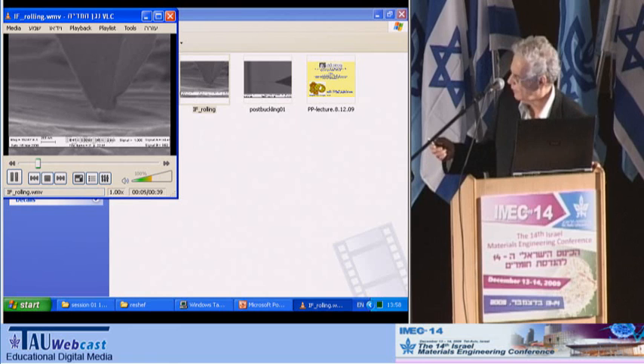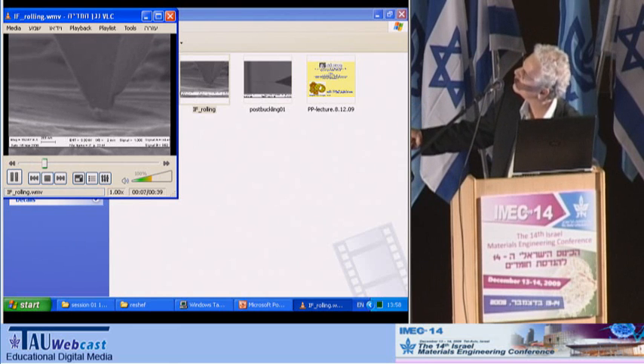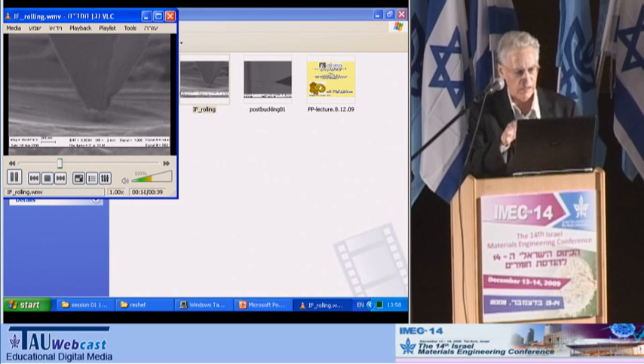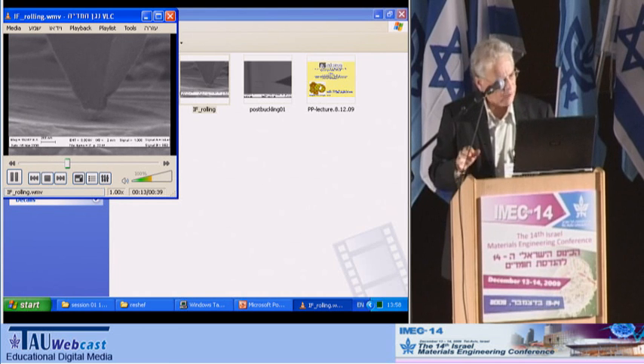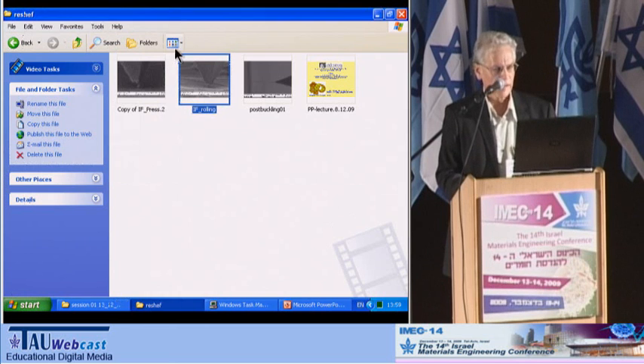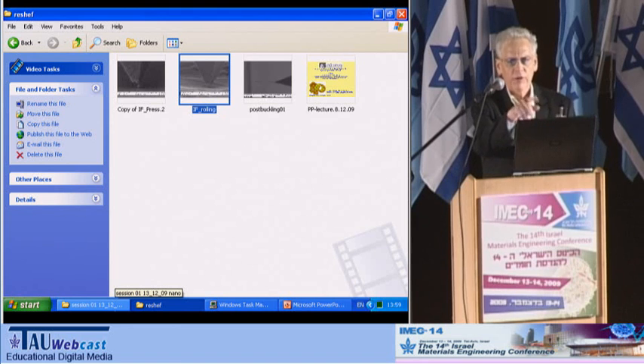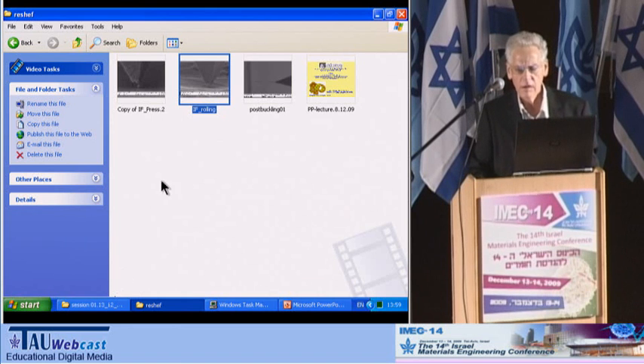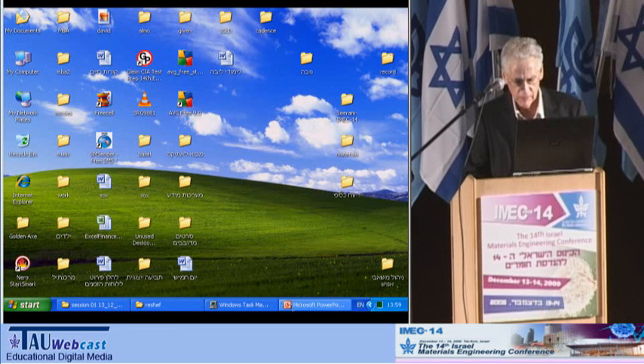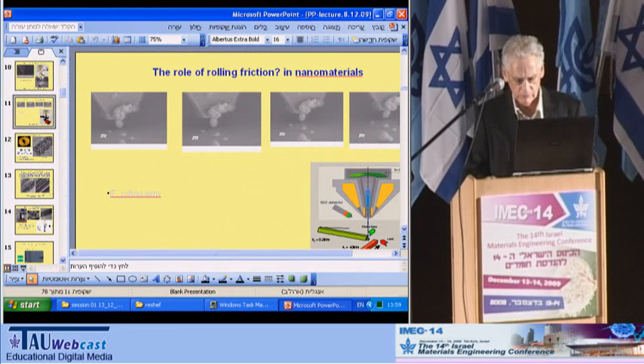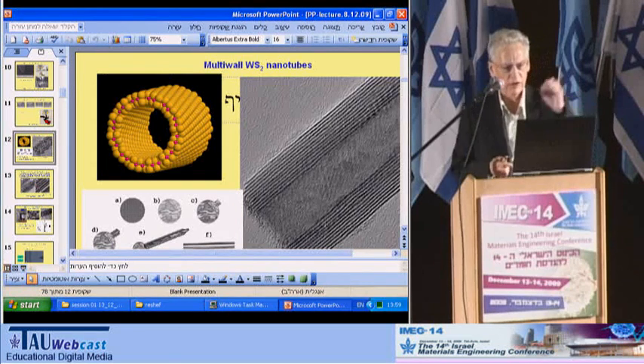You can see the nanoparticles. The nanoparticle is not only loaded, but it's sheared, and there is a very nice shearing process and rolling of the nanoparticles, and some sliding too that occur in this case. When the nanoparticles are entrapped in the contact area, it's more difficult for them to rotate, but nevertheless, they can do some of their rotation, and they can benefit from their regular spherical shape.